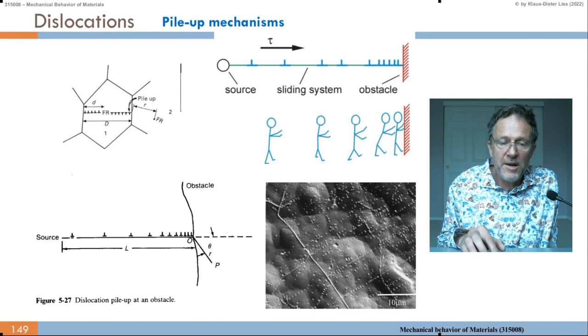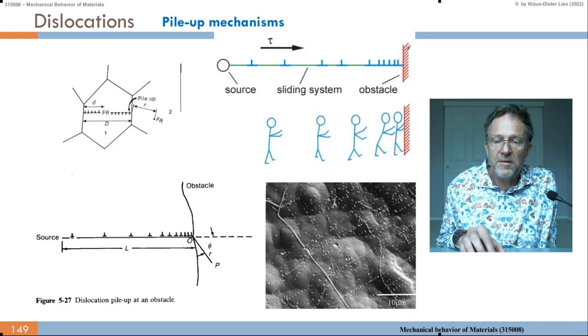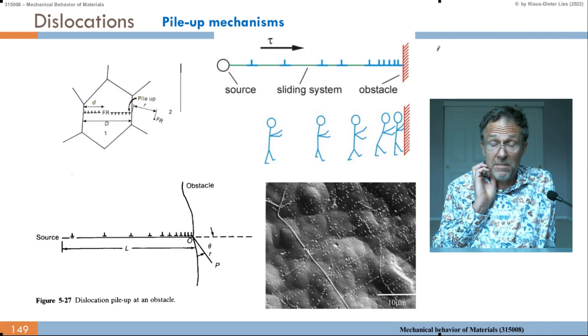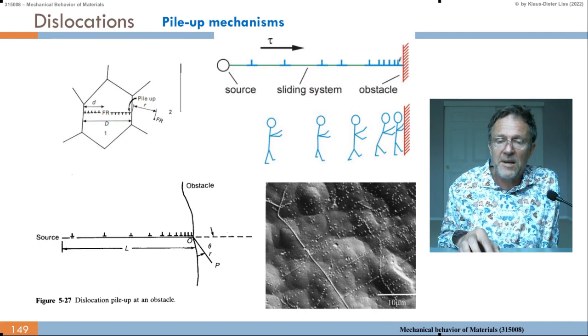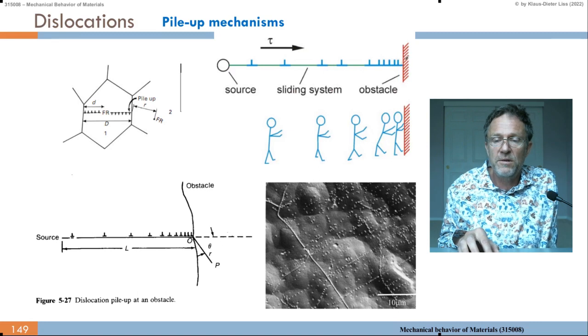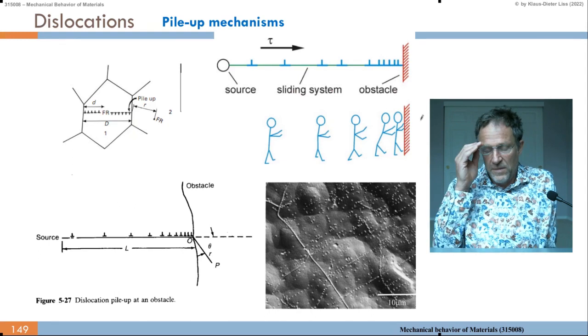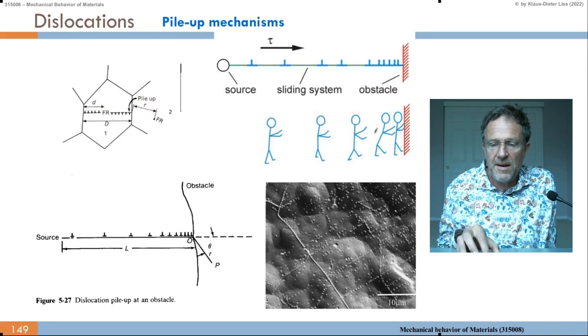So there's some big energy barrier, but eventually it can go through, introducing a new dislocation or continuing the dislocation in the next grain. One dislocation moving there may not have enough energy to penetrate the wall. But now, if the second dislocation comes and also pushes to the right, it wants to move to the right, it would lower the energy, that's why it moves. So it builds up a force. The force is given by the first dislocation pushing on the wall, and then the second dislocation pushing the first dislocation, pushing on the wall. So, two people pushing gives you twice the force. And then the next one comes, gives you 3 times the force, 4 times the force. So it gives you many times the force until it can go through the wall.